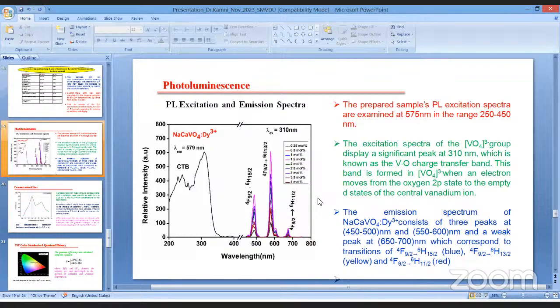And you can see the emission peaks. There are 3 emission peaks, 2 very strong peaks, and one very weak peak also. The emission spectrum of this sample consists of 3 peaks, the first at around 450 to 500 nanometer. The second one is at around 550 to 600 nanometer, and a very weak peak is also observed at around 650 to 700 nanometer, which correspond to various transitions.